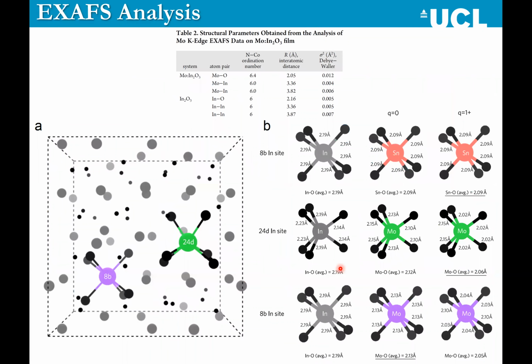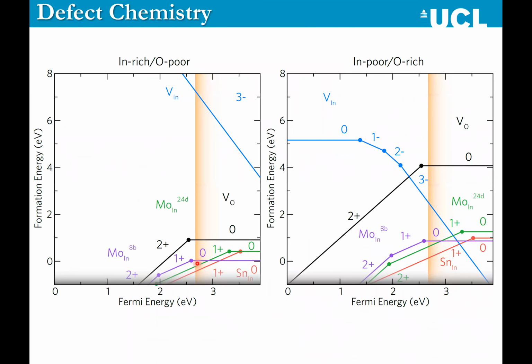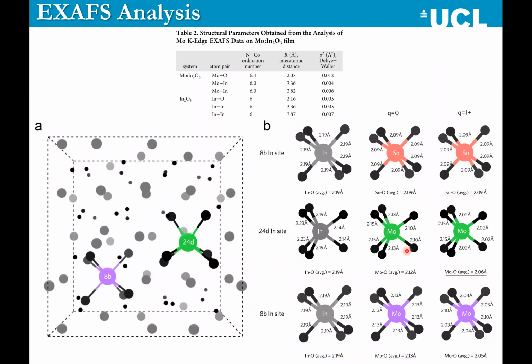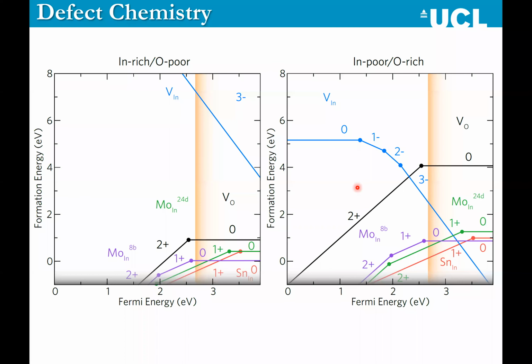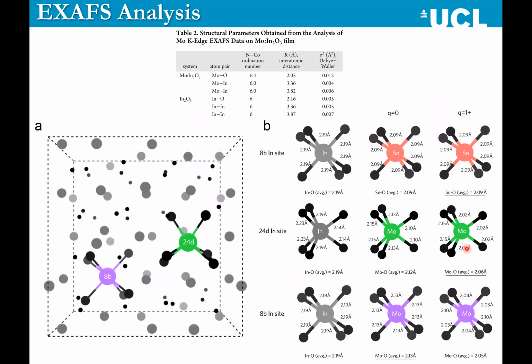So we did some XAS measurements to analyze the bond lengths around the molybdenum in the indium oxide matrix, and we kept coming out with a distance of about 2.05. When we did our calculations for the neutral charge state, which would be these flat lines here for the purple and the green, we found that the bond lengths were about 2.09 and 2.12, which didn't really fit with what was being seen in experiment. But when we looked at the +1 charge state, where the electron is no longer associated with the defect and is actually zipping around in the conduction band minimum, and which are, of course, the lower energy numbers, these sloped lines here for the purple and green, then they actually get much closer bond lengths compared to experiments, which is what is seen in the XAS measurements.